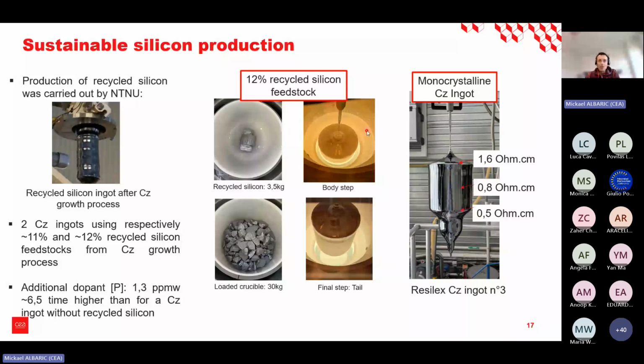Here you can see the final step, so the tail. This is the last part of the ingot that has been pulled before the experiment finished. On that ingot, we measure at the ingot level the resistivity, so we can confirm that we are in a good resistivity range, in the range of 1.6 at the top to 0.5 ohm centimeter at the bottom of the